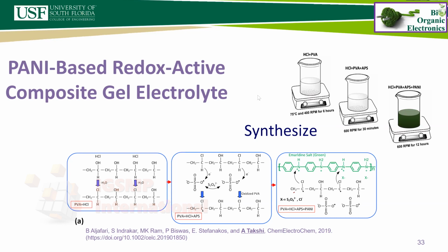So we went for a very simple process of taking polyvinyl alcohol, mixing it with an acid, and then adding an oxidizer, APS, and then adding aniline as a monomer. And then we got the in situ polymerization to produce polyaniline. So as you can see, just by mixing different materials in a beaker in 3 steps, we generated some sort of colored gel, which we know has the polyaniline inside.